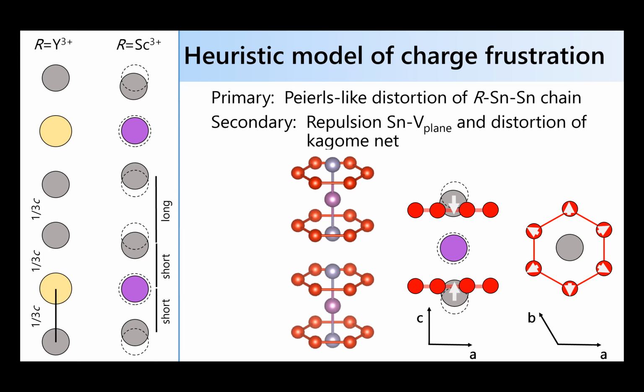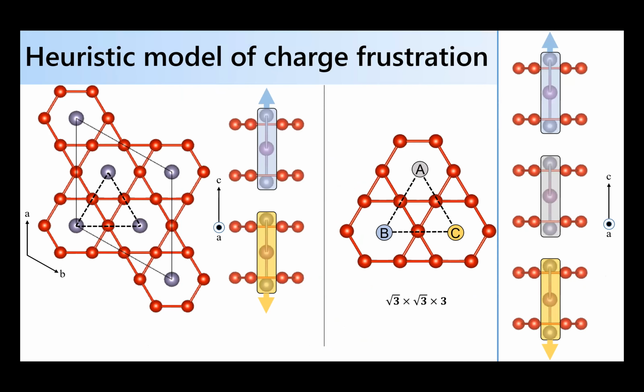But once you put scandium in, which is a smaller atom, basically you allow for an instability in which the tin atoms can move in closer to the scandium ion, okay? But as they do so, now this is adding in the hexagons from the vanadium-based kagome network. When this tin atom tries to move towards the scandium, they have to move closer to this vanadium hexagon, and there'll be a steric effect or an energy penalty for that, right? And so what they'll try and do then is one of these, what I'll call trimers, will try and move up, and the other one will try and move down relative to each other to try and minimize their energy. This is like a heuristic model of what's going on.